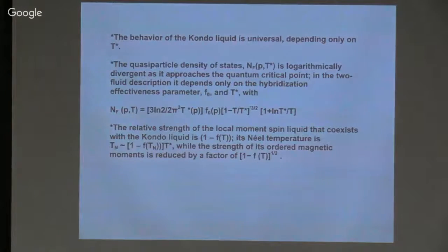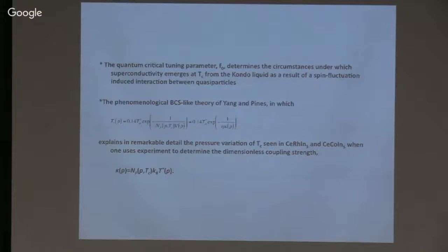What was surprising to us is that if you now take the phenomenological theory seriously, you have a very simple expression for your density of states for the Kondo liquid. And it's going to notice that it's going logarithmically like T star over T. And the relative strength of the local moment is 1 minus F. You have a Néel temperature that's reduced by the 1 minus F times T star, and the strength of the moments is down by a factor of that to the 1/2.